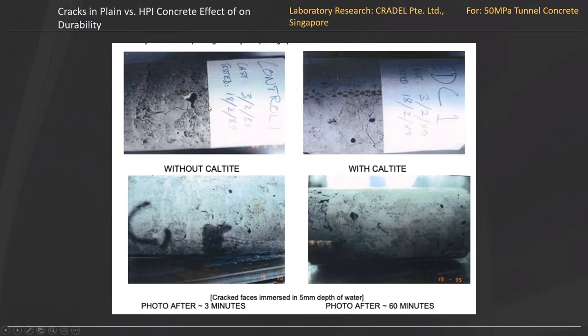But these are reinforced samples of concrete, and they've been artificially cracked and then just literally immersed in water. You can see this is ordinary concrete, and it's immersed in a shallow bath of water, and you can see just after 3 minutes how capillary rise has taken that water up into the concrete there, up to the level of reinforcement. Whereas the one with the HPI, this photograph was taken after 60 minutes, and there's no sign of any water ingress going into that crack.